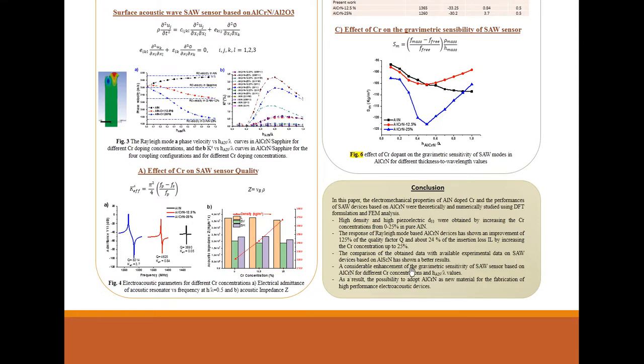A considerable enhancement of gravimetric sensitivity of SAW sensor based on aluminum nitride doped with chromium for different chromium concentrations and different thicknesses of aluminum nitride. As a result, the possibility to adopt aluminum nitride doped with chromium as a new material for the fabrication of